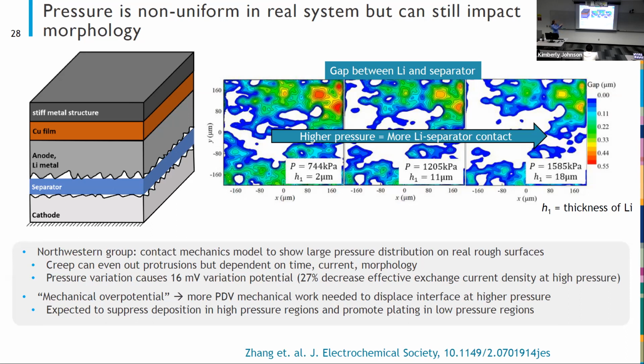And then what they did after they got these images was throw the pressure distribution into what we call the Butler-Volmer equation, which is an equation to understand the kinetics of an electrochemical reaction at an interface. And in that equation, there is a term that is related to pressure and mechanics because you have to do work to move something mechanically. And if you plug the changes in pressure into that equation, you get that there will be about a 16 millivolt variation in the overpotential that you will need to drive this reaction in a high pressure region versus a low pressure region. And so that means there's an incentive for lithium to plate at the low pressure regions because we don't have to pay the penalty of this overpotential.